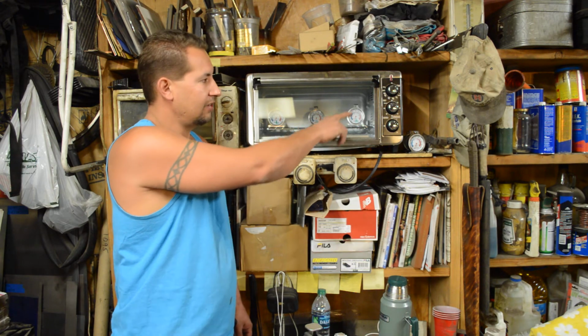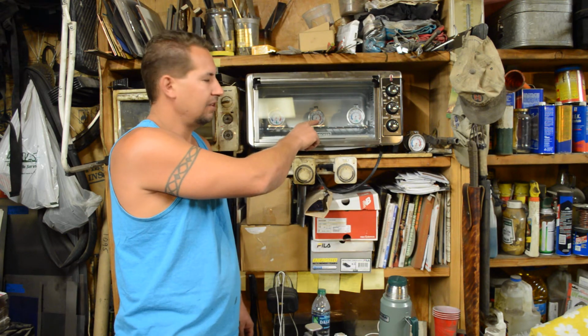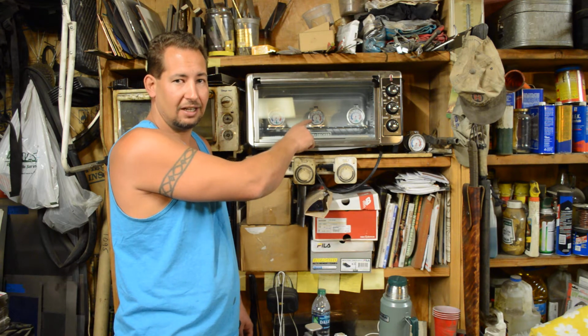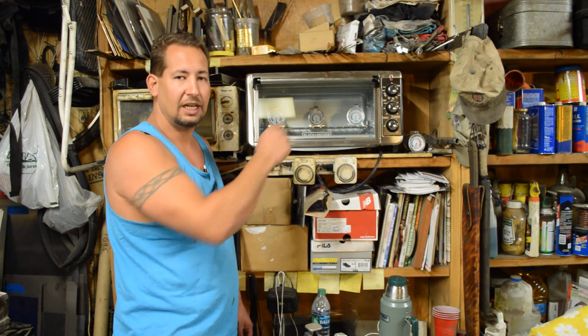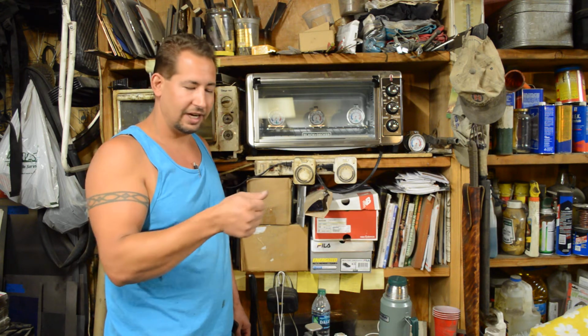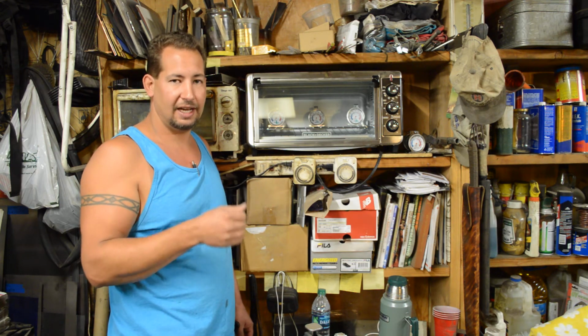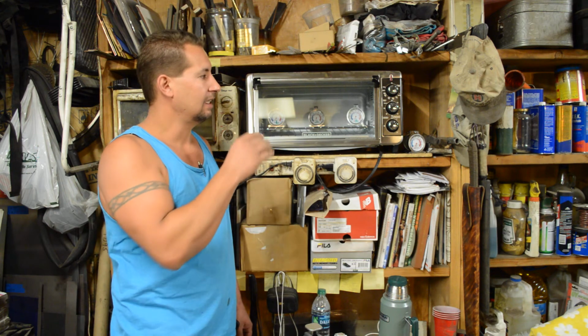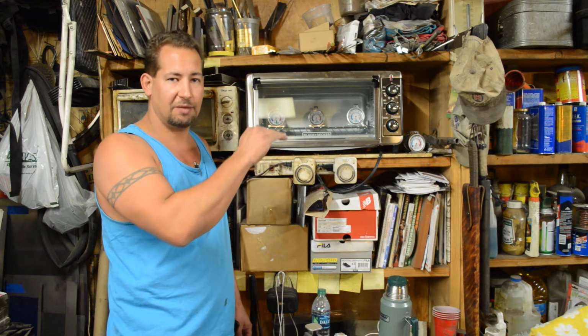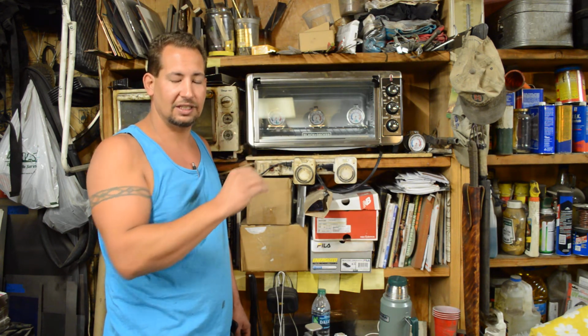Okay? Now go ahead and adjust your temperature knob to where you get another 10 to 15 degrees higher on your thermometers. Put the knife back in for another 2 hours. Pull it out, check it over the brass rod, deform the edge, see if it's still chipping out. You keep doing that and keep going up in 10 to 15 degree increments until that edge no longer chips or until the edge fails the way you want it to fail.